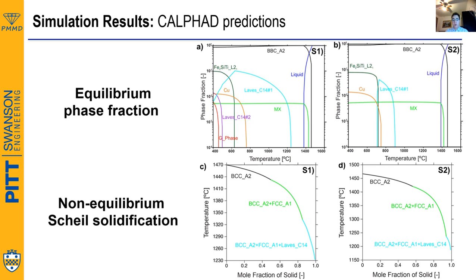Now, this titanium-silicon difference has a more drastic effect when it comes to the Laves phase. Clearly, we notice the drastic difference between S1 and S2, where S2 has a very narrow, condensed temperature window where the Laves phase can exist, while in the case of S1, the Laves phase is predicted to exist all the way up to 1200 degrees C.